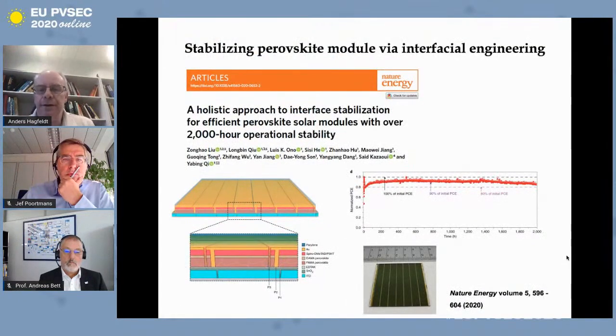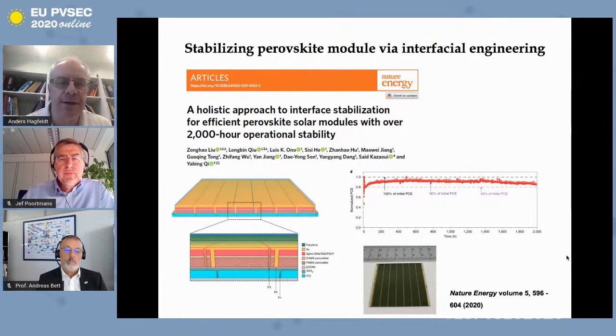I noted a very interesting report on also scaling up like modules, and this is a report from Yabing Qi and others in the team where you do see 2,000 hours of very good stability for modules, and this comes also from passivation of all interlayers from the tin oxide to the perovskite to the spiro layers. So this also demonstrates passivation effects and a very promising stability test.